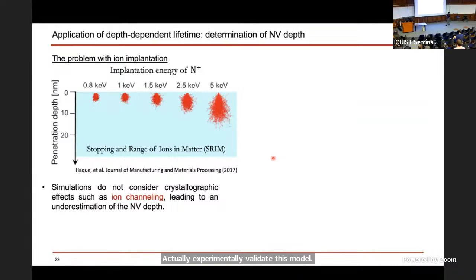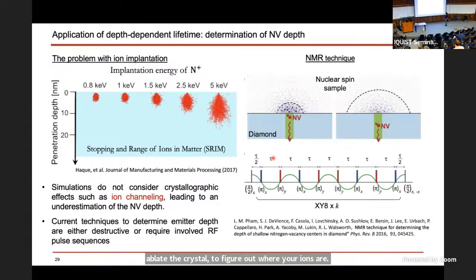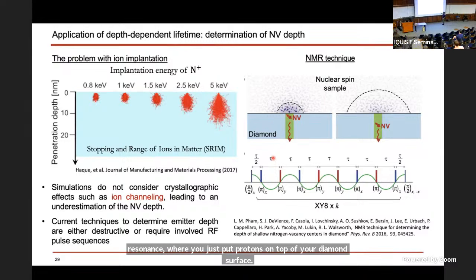So we found one potential application, which is that in general, it's not that easy to find the depth of these color centers after you've ion implanted them. There are a couple of good methods that have some drawbacks. As I mentioned, typically we use ion implantation, where you can predict roughly where the ions would end up through a Monte Carlo software called SRIM, but it doesn't predict certain behavior like ion channeling. You can do something called TOF-SIMS to literally ablate the crystal to figure out where your ions are. And there's also a nice technique based on nuclear magnetic resonance, where you put protons on top of your diamond surface and use the near-surface NV as a probe for these protons, which allows you to extract their distance.